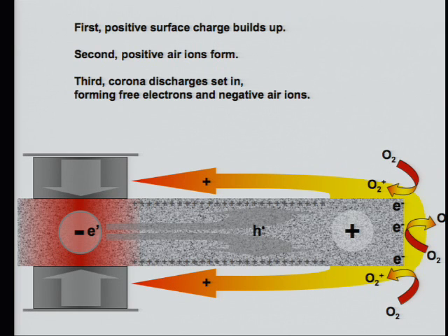Now, when we did this experiment, and I will show you the results, we did these things this summer. That is very recent stuff. And Ipek and Gary were involved in this work. We found that, as expected, the first thing that we see is that a positive surface charge builds up. Easy to measure. We just put a capacitor plate and measure the voltage between that capacitor plate that floats over the surface relative to the piston. We can measure that battery voltage.